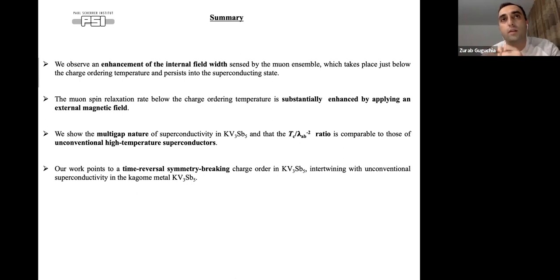And what is happening in zero field is that you have a change of the electric field gradient across the charge density wave transition, which would also change the coupling between the muon and the nuclear moments. So that's why we cannot really say clearly whether the change is just because of the charge density wave, or because of orbital currents.